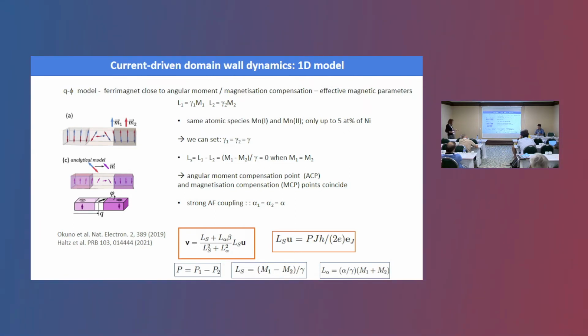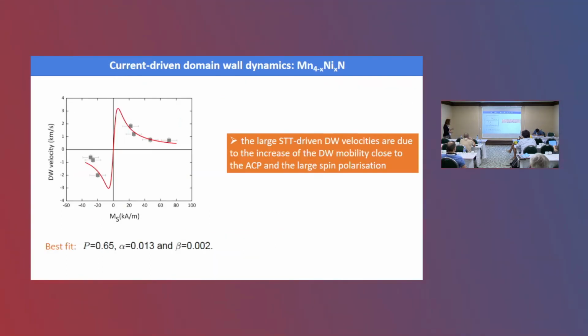So the velocity is given by this expression, and then you expect that the domain wall velocity would be vanishing close to the angular compensation point. So we fitted our data with this formula, and this is the best fit that we could obtain. And there are three parameters: the spin polarization, the damping, and beta, that is the non-adiabatic term for the spin-transfer torque. And then you can see that we have this very small contribution of the magnetic torque and this large magnetization.